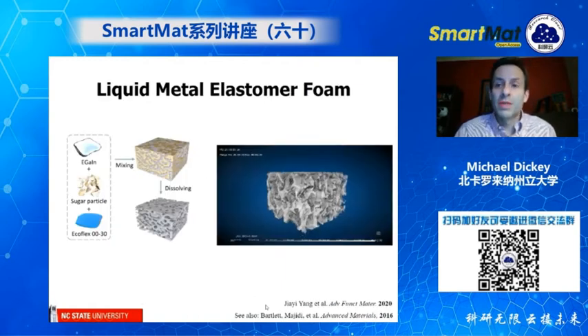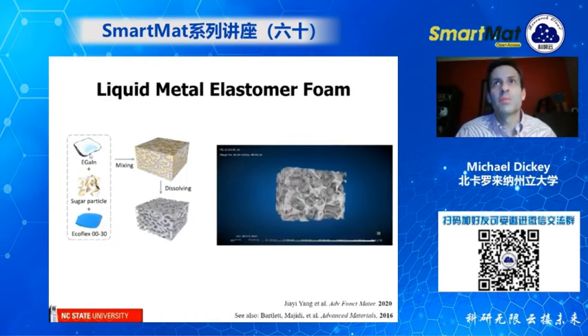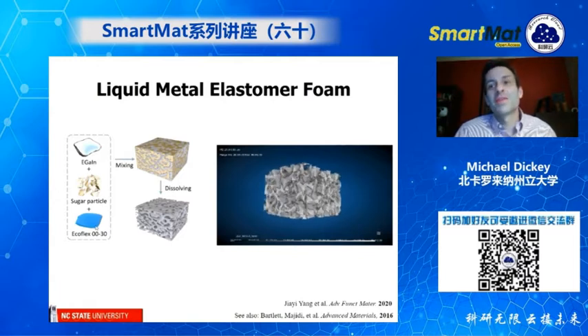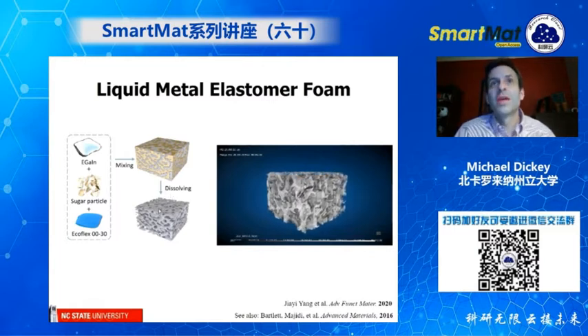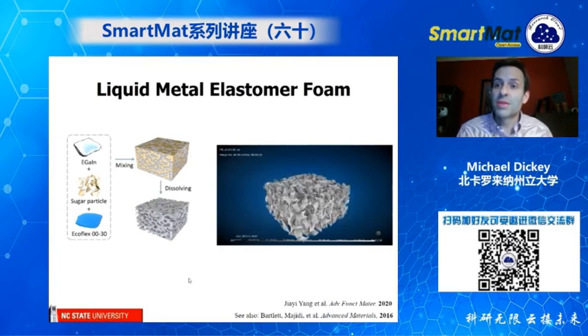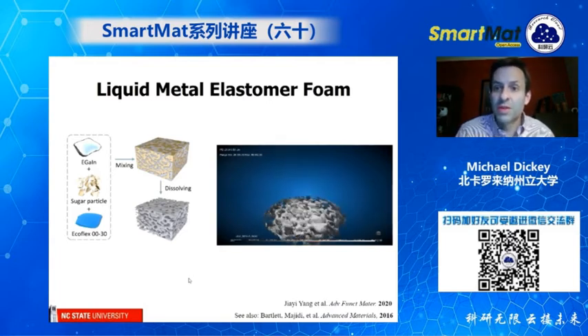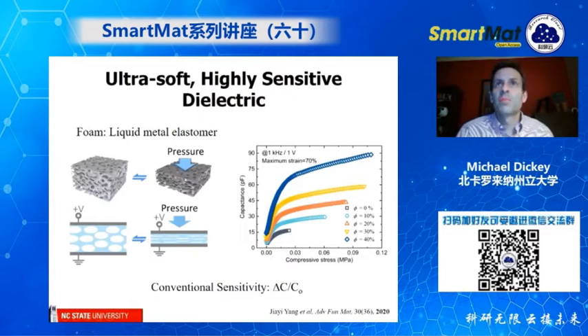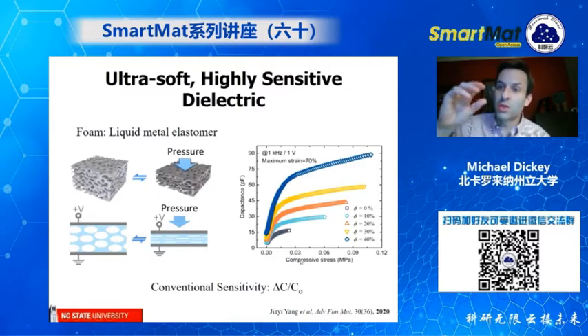And so anyway, we did this, and we mix liquid metal. So here's the liquid metal with some sugar and some silicone called EcoFlex. And we mix them together, and then we dissolve the sugar, and that leaves behind a foam. So you can see this is what the foam looks like. The foam consists of the liquid metal mixed with the silicone. And so as a result, it's very, very soft. And so the beautiful thing here is if you take this foam and push on it, you effectively increase the dielectric constant. And so this is very, very soft, and you have a high dielectric constant. And so we can measure this change in capacitance as a function of stress, basically, as we push on this material. And there's several sets of data here, from 0% liquid metal all the way up to 40%.